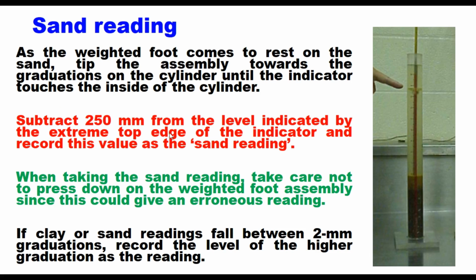Subtract 250 mm from the level indicated by the extreme top edge of the indicator and record this value as the sand reading. Now when taking the sand reading, take care not to press down on the weighted foot assembly, since this could give an erroneous reading. If clay or sand readings fall between 2 mm graduations, record the level of the higher graduation as the reading.